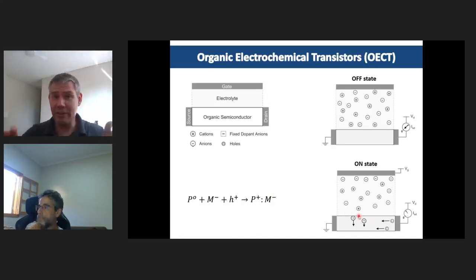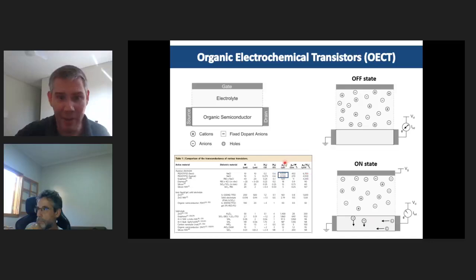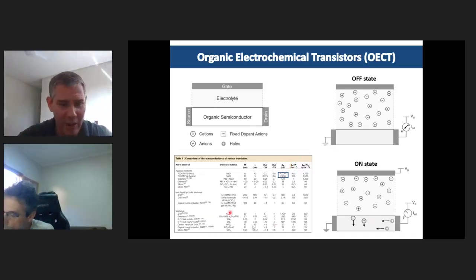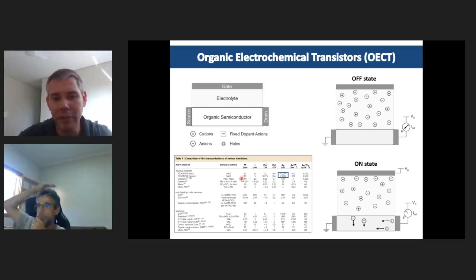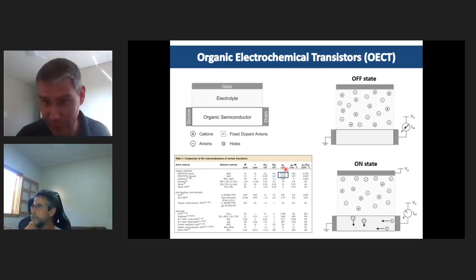And again, those ions enter the bulk of the material. And therefore, there is a lot of space to receive charges. And therefore, the capacitance of these devices is huge. And by having a huge capacitance, you also have very, very big transconductance, which is basically the on-off ratio. And by this chart here, you can see that OECTs, here PEDOT:PSS is another very important material in the field, are by far one of the highest transconductance transistors among several technologies. And by having a very big on-off ratio, you also have a very high resolution for transducing ion to electron fluxes.